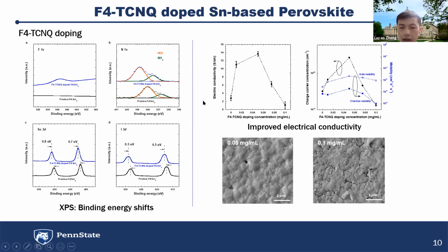We can see that by adding only a little bit of F4-TCNQ, we can dramatically boost the electric conductivity, almost over three times compared to the pristine film. And the increase and decrease of the electric conductivity is consistent with the mobility and charge carrier concentration we measured.